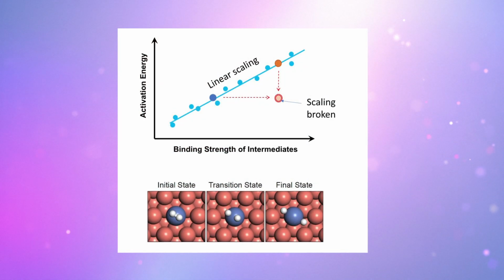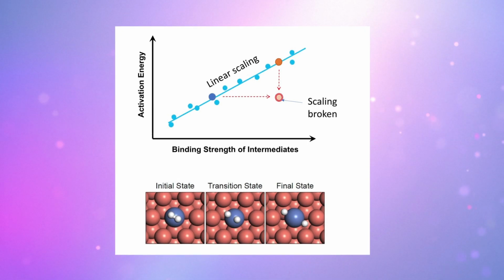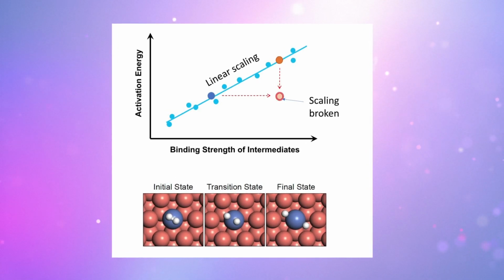And for example, in a lot of the reactions, the transition state is above the atom, and the intermediate binding site is at the side. So you decouple those two things and you can break linear scaling. You can get both low activation barriers and weak binding and selective chemistry. So that's been a real learning experience for us, to shift away from the mean field argument of the older work. That was a big surprise.